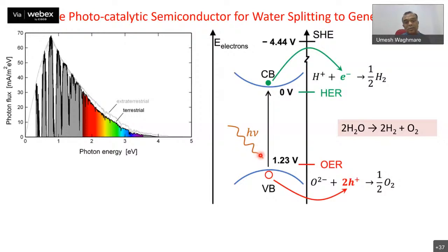If you absorb solar radiation, it generates a hole-electron pair, and this electron is used in the reduction of hydrogen in the hydrogen evolution reaction to generate the H2 molecule, and the hole is used in the oxygen evolution reaction, whose redox potential has to be just above the valence band, and the redox potential of HER has to be just below the conduction band. And the gap between these two redox potentials is 1.23 eV. So the gap of a semiconductor has a lower bound of 1.23 eV. So we can't use this part of the radiation.